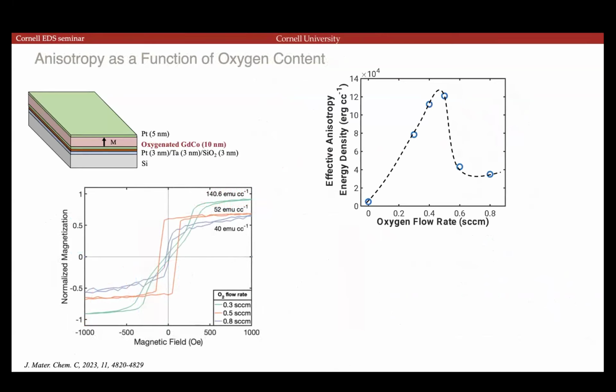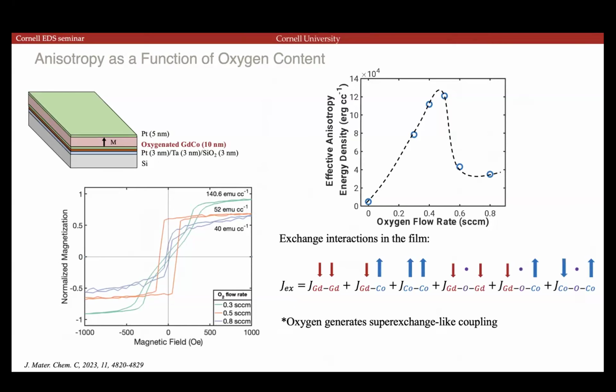As I mentioned, we saw high anisotropy in my postdoc because of oxidation. So we also varied the oxygen content as a function of flow rate during the growth and optimized the peak at which we see the largest amount of anisotropy energy. The reason why oxygen is improving the anisotropy is due to what we call in magnetism super exchange. So if you look at the different interactions of all the elements within the film, either gadolinium